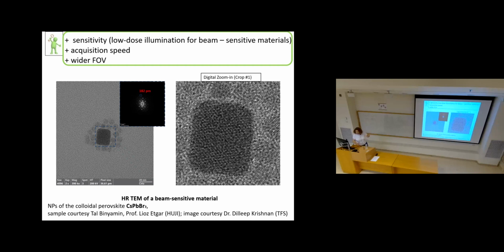And it comes with organic solvents and ligands on top, so the contamination rate is also very high. So here the sensitivity and the acquisition speed are even more important than the resolution because the lattice is not that small. This is not gold and not iron. This is a compound with quite large interatomic distances, but we can get quite a nice image with a resolution of 0.18 at least, and with high contrast with this new CETA camera and with very high speed. The image was acquired in less than 1 second. And also, because of the 4K by 4K matrix, the option is to acquire a large field of view and then go for digital magnification. I will show you in the second slide, I think.